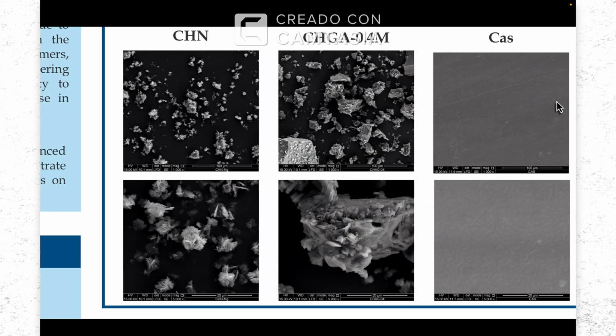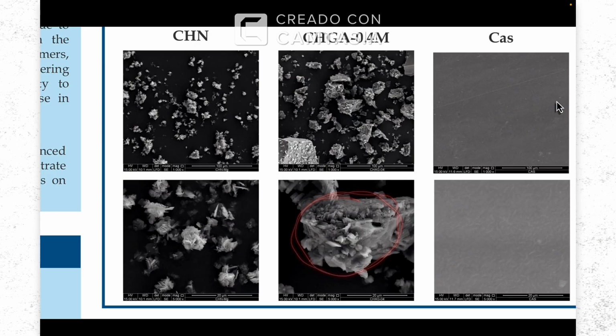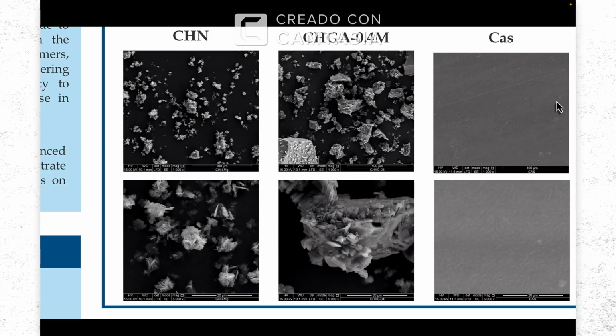The scanning electron microscopy showed an important change in morphology after the intercalation of the material. We can observe the material is more compact than the original copper hydroxynitrate. This is another evidence that we get a successful functionalization of the material.